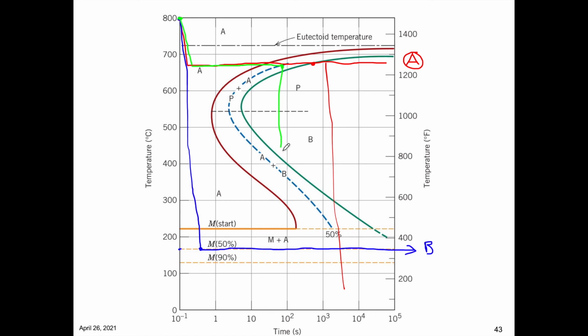And then here's where it starts to look a little tricky. So once we've cooled to a lower temperature, the process starts over. So we actually need to kind of go back in time effectively, go back to the start at 0, because once we're at a new isothermal temperature, we start over in time.